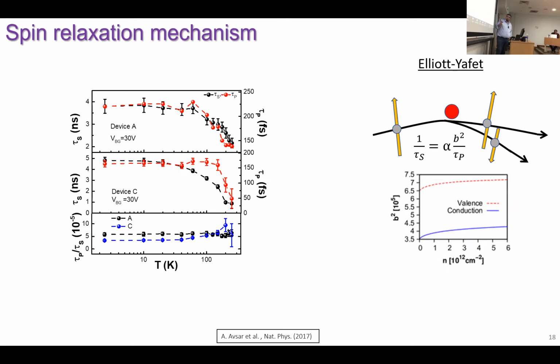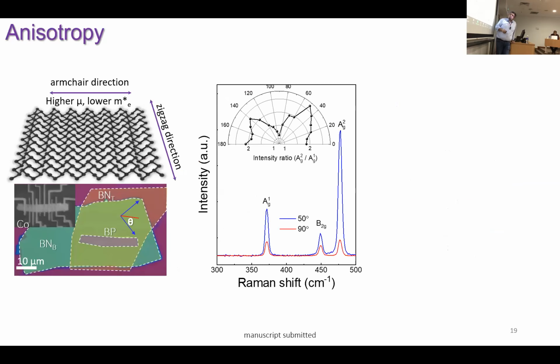And our collaborators did some calculations for us. So this is called spin mixing probability. The one that they found theoretically is almost identical to what we measured experimentally. This might be trivial to you, but in the case of graphene, these experimental and theoretical values differ from each other by almost 1,000 times. So it was quite good that by doing the right fabrication in the glove box environment, we managed to almost reach the intrinsic spin transport properties of this material.